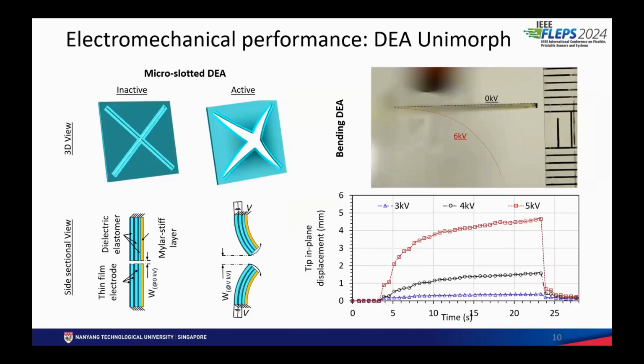And as I mentioned before, we try to use the bending form of dielectric elastomer actuator for this device. This is how it looks when we activate the device. Here, the video shows only one section of this cut. We have some form of dielectric breakdown when we apply voltage above 6 kilovolts. So for all our applications, we restrict the applied voltage to below 5 kilovolts. We are able to obtain quite good tip displacement. The maximum tip displacement we can obtain at 5 kilovolts is about 5 mm.